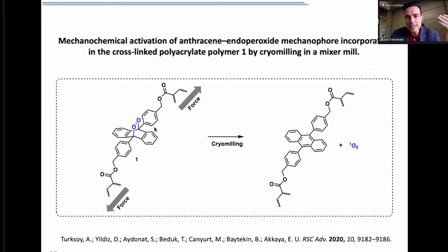Also, they demonstrated that polymer number one was stable at high temperatures. Demonstrated in that way that indeed, by milling, you could activate the mechanophore within that polymer. In other words, that you could harvest the force that you generate and leverage that force throughout the polymer, and the polymer was working as a medium to transduce that mechanical force.